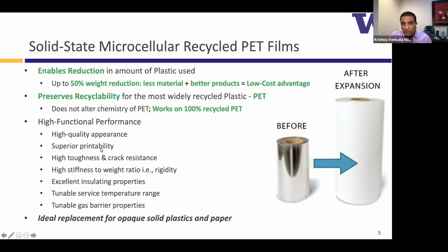So very high quality appearance, superior printability, very high toughness and crack resistance, high stiffness to weight ratio, which is the original goal, good insulating properties. We can tune the service temperature range by just using CO2 gas to crystallize the material. So the service temperature of PET, which is typically not more than 60 centigrade, can be increased all the way up to 220 C in some cases. And then tunable gas barrier properties for oxygen barriers, specifically for shelf-stable foods, is a really important property, right?